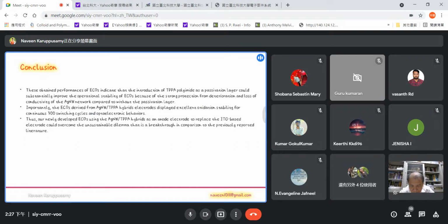Then after the passivation layer, they performed this cyclic stability test. After 300 scans, it shows greater stability. There is a slight change in the anodic and cathodic peak current. After the passivation layer, they achieved good stability over the silver nanowire.